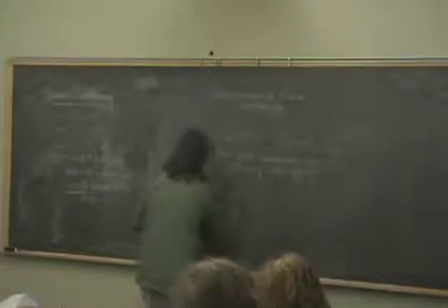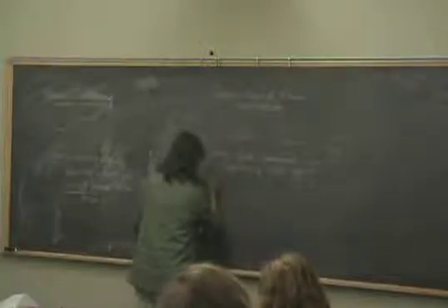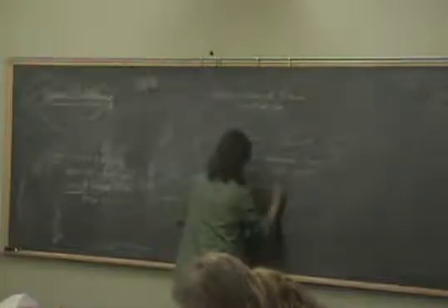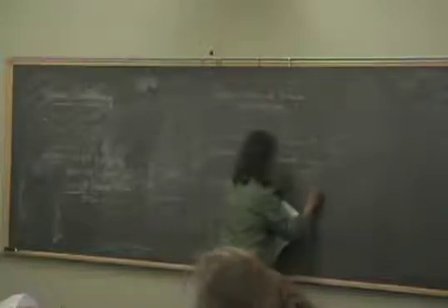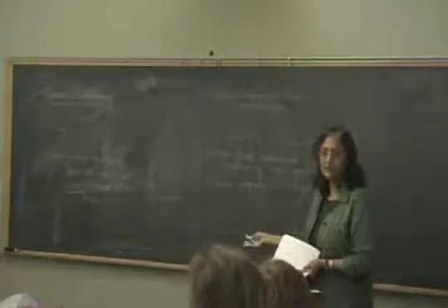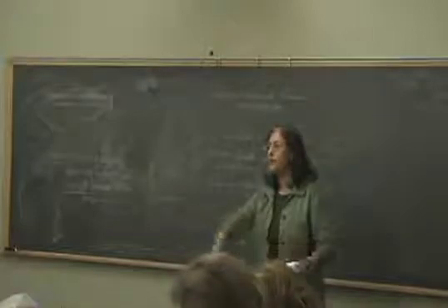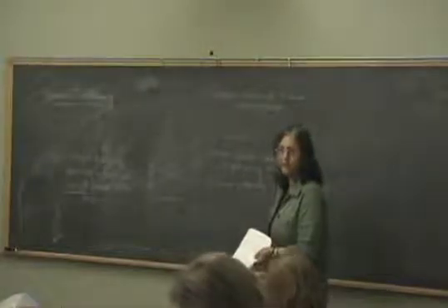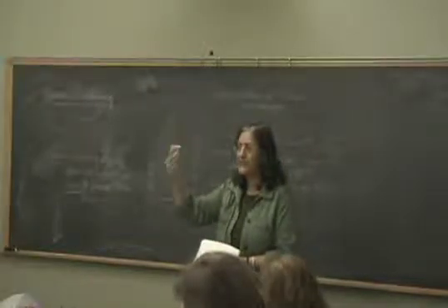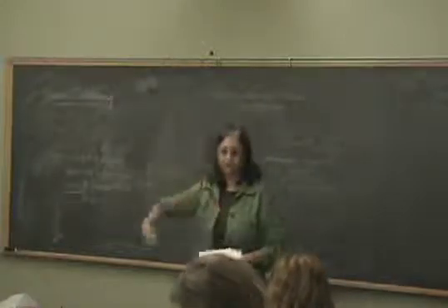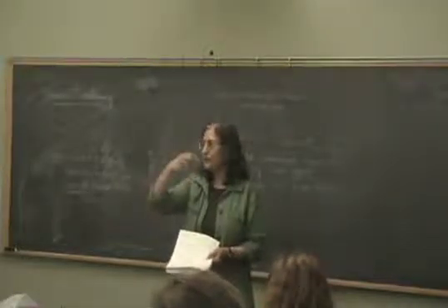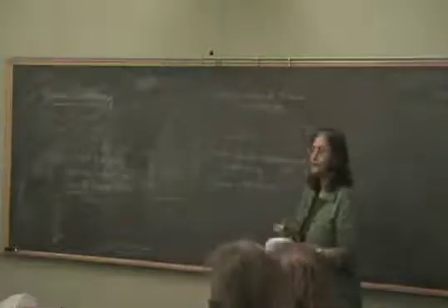Okay, so the main thing I want to write down is that the Raman intensity is about 1,000,000 times higher. And that is what allows you then to do local imaging. Otherwise you're relying on many, many molecules giving you that factor of 1,000,000, because you have a certain detecting capability, and unless you have a signal of that amount, you can't detect. So previously you were relying on 1,000,000 atoms' worth of material giving you that much enhancement. Now, because the signal has become 1,000,000 times higher, you can go down that much in the volume that is responding.